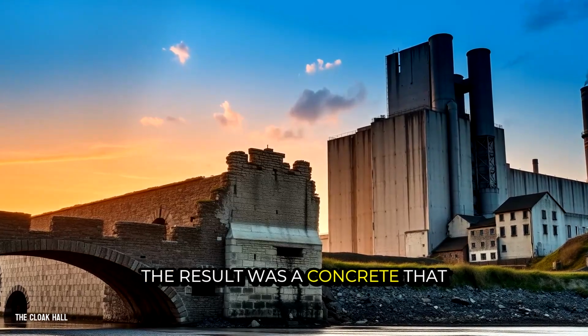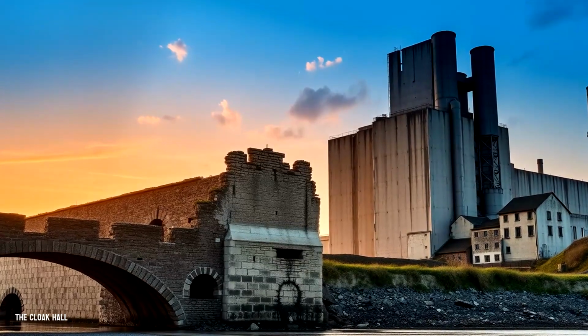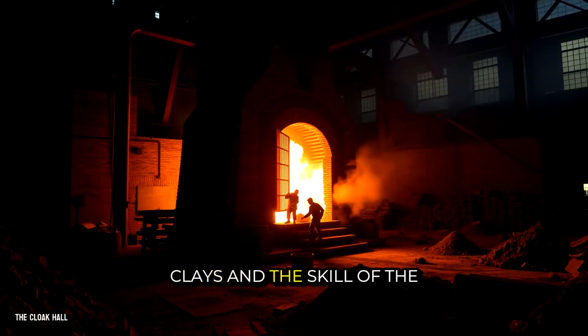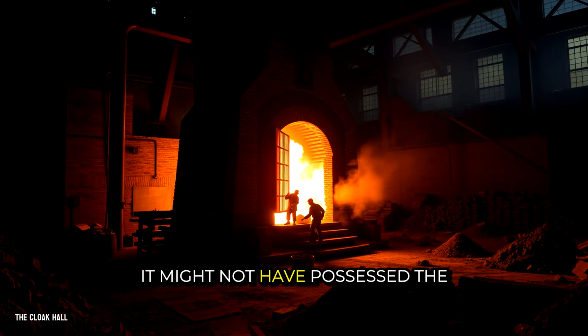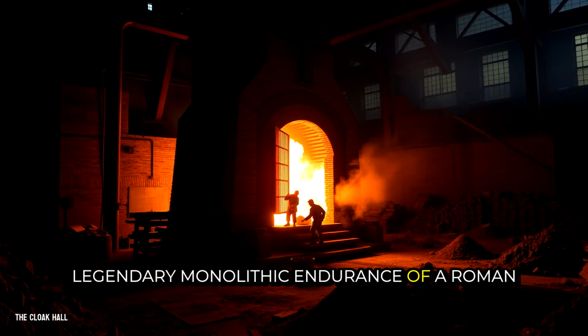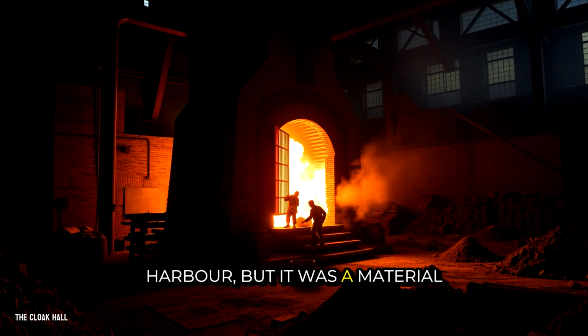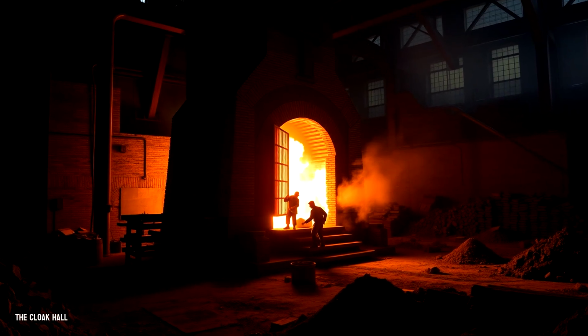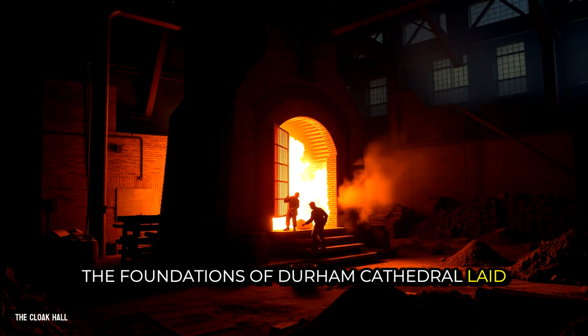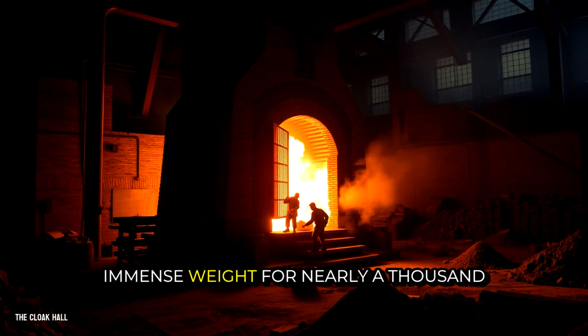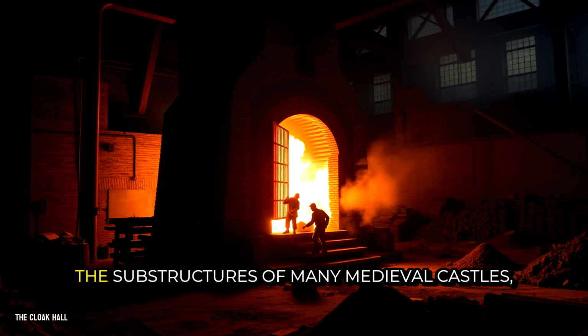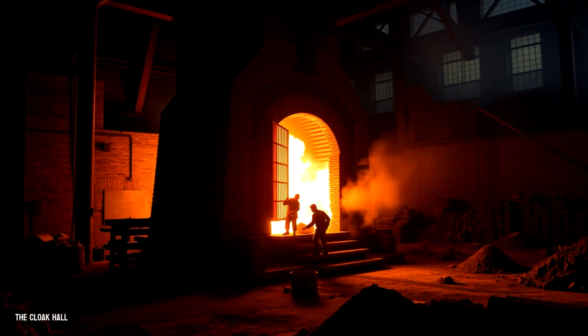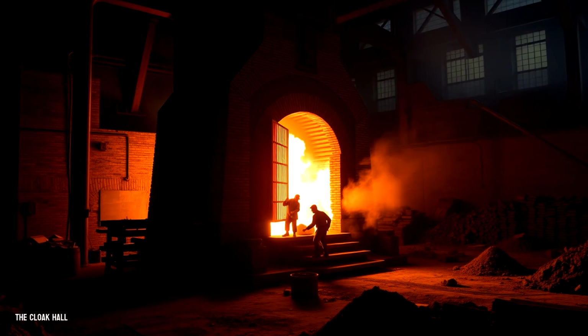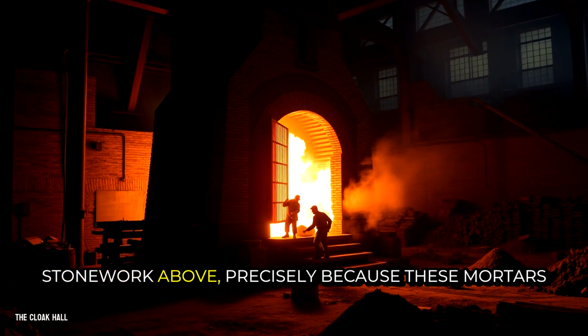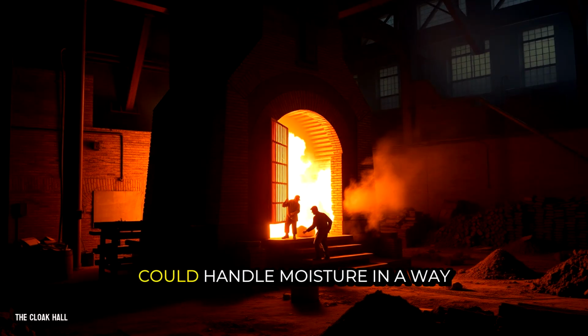The result was a concrete that varied from region to region, its quality dependent on the local clays and the skill of the burn. It might not have possessed the legendary, monolithic endurance of a Roman harbor, but it was a material of remarkable resilience. The foundations of Durham Cathedral, laid upon such a mortar, have borne immense weight for nearly 1,000 years. The substructures of many medieval castles, constantly damp from moats or earth, often show less decay than the stonework above, precisely because these mortars could handle moisture in a way modern concrete cannot.